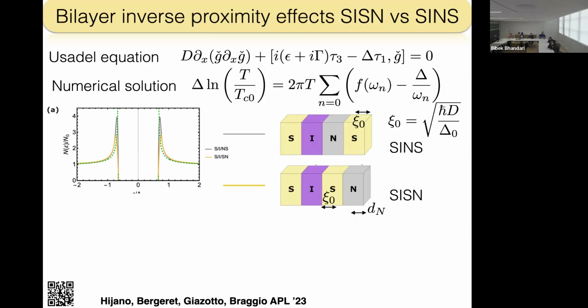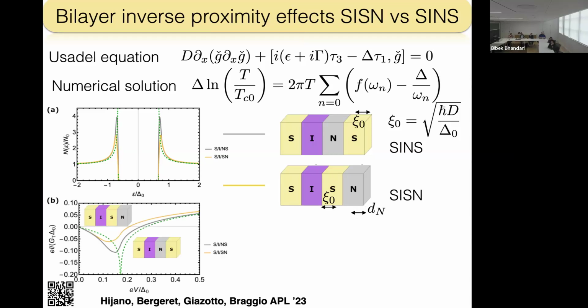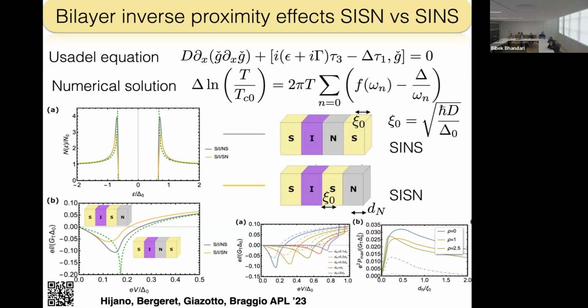Now we made this type of junction. For us it was obvious that this is the good one, because here there is a superconductor, so I would expect the density of states to be very peaked. However, things are not so simple. If you make the computation using this equation, you can compute this configuration, and you see that the inverted configuration is even better. So probably in our experiment, you remember we got this type of smoothed curve, and the smoothing is probably due to the fact that we chose this geometry instead of this one. So you can even improve a little by changing the way you make the junction, the geometry, and now we have full control even of the thickness. So we have a little more control over how to produce a good